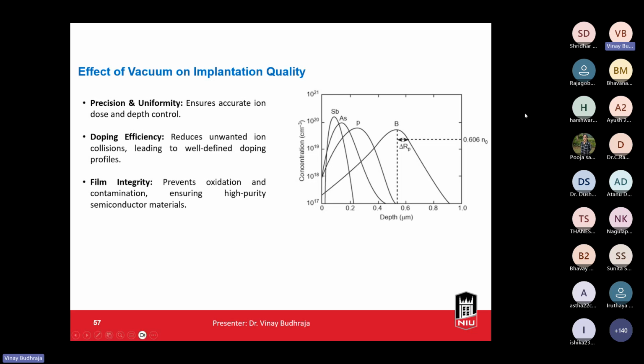The depth profile in ion implantation and in diffusion is very different. This is the typical concentration with respect to depth in ion implantation. We mainly see a good Gaussian. We need a good peak intensity, and that is maintained with the help of vacuum. Otherwise, other gases and materials will be present, which can affect the film quality and result in a poor junction in the semiconductor devices.